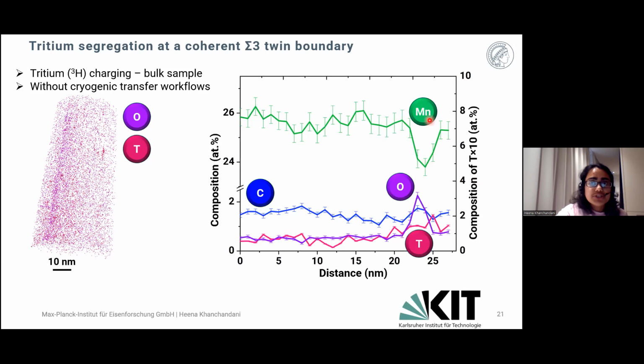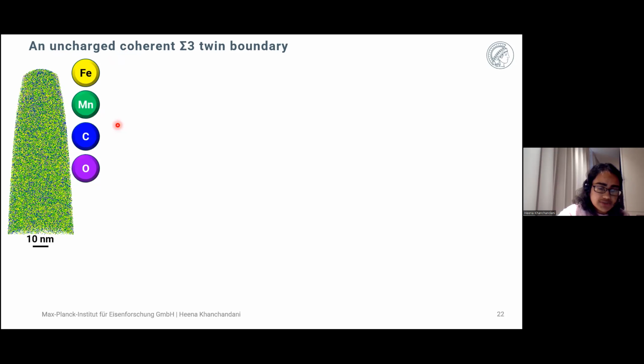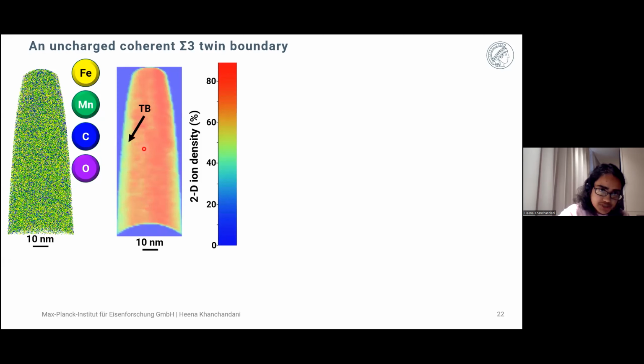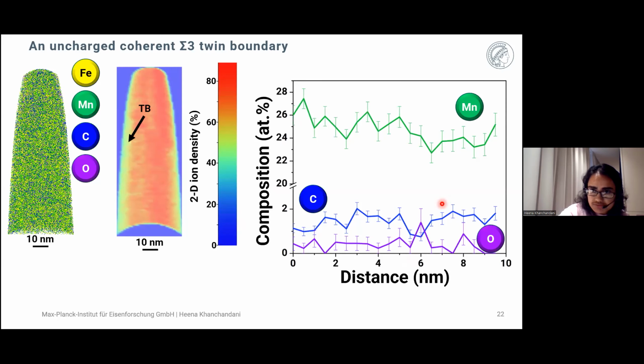So, and there was also depletion of manganese. This oxygen segregation was inherently from the material used for the analysis itself, and it got segregated at annealing twins probably during the annealing treatment, because it is also present in the uncharged coherent sigma-3 twin boundary. So here is the coherent sigma-3 twin boundary, which was analyzed from the uncharged material, and it does not have any elemental segregation. So we identified it from the density fluctuations in the 2D ion density map. And it also had the oxygen segregation with manganese depletion.